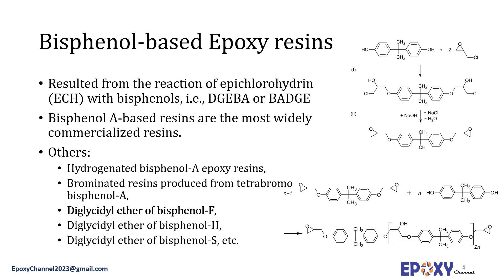The most common epoxy resins are based on reacting epichlorohydrin with bisphenol-A, resulting in a chemical substance known as bisphenol-A diglycidyl ether, commonly known as BADGE. As shown in the figure, in this two-stage reaction, epichlorohydrin is first added to bisphenol-A, then bisepoxide is formed in a condensation reaction with stoichiometric amounts of sodium hydroxide. The chlorine atom is released as sodium chloride (NaCl), and the hydrogen atom is released as water.